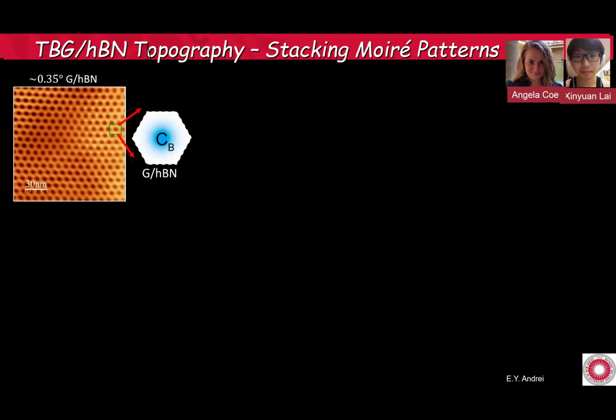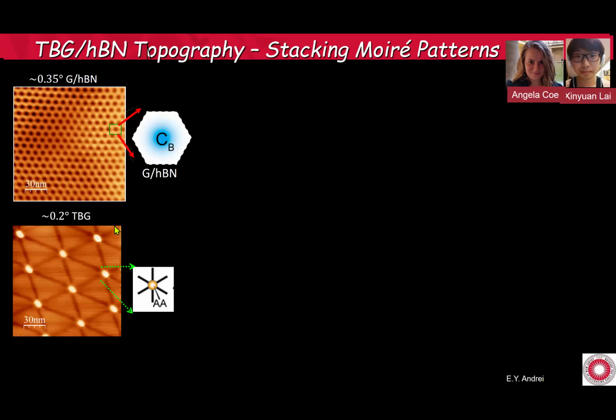When you put graphene on boron nitride, carbon sitting on boron is going to look like this: a dark region with a bright halo around. And when you put graphene on graphene, you're going to get these very bright points, bright regions, which are the AA lattice. And now you superpose the two.